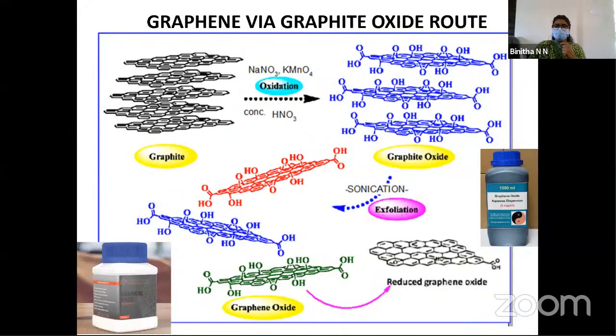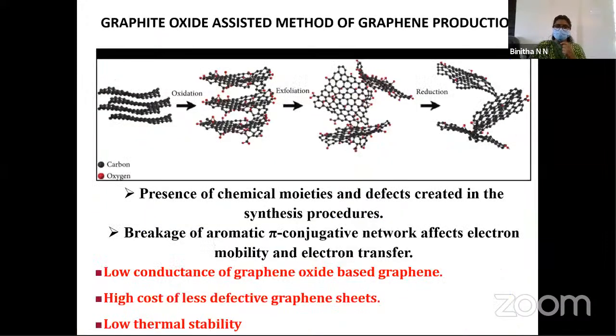We cannot call it simply graphene, it is reduced graphene oxide because some of the oxygen functionalities are still there. In addition, the drastic oxidizing conditions cause some defects in graphene. Graphene oxide is available even in the market, and it is a large scale, low cost method, and so everyone prefers graphene oxide. But there are some functionalities even after reduction, and defects in the sheets. So it will break the aromatic pi conjugative network of graphene, and it will affect the electron mobility and electron transfer. The conductivity of graphene oxide will be less than that of graphene, and so we need less defective graphene sheets for electronic applications, but they are costly.